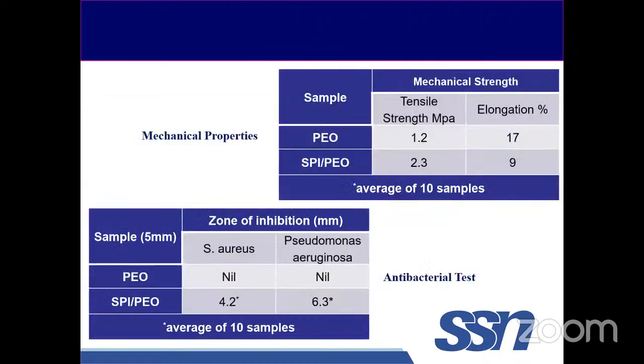We also tested the mechanical properties of the prepared material, where, as I already mentioned, SPI is a globular protein, right? As I blended it with PEO, the tensile strength of the material increased from 1.2 megapascal to 2.3 megapascal, and the elongation decreased from 17% to 9%. And as arginine and glutamine have good antibacterial activity, the zone of inhibition was also seen when we tested the antibacterial activity against both gram-positive and gram-negative bacteria.